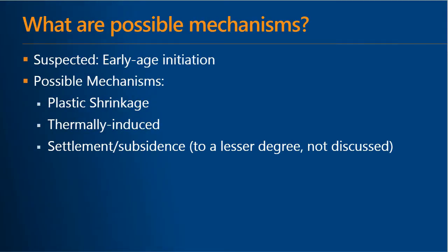So if we were to see this in the field, we would start thinking about early age initiation of those cracks. And so some of the crack mechanisms that immediately come to mind would be plastic shrinkage cracking, thermally induced cracking, and potentially settlement or subsidence, although that somewhat to a lesser degree, and I'm not going to discuss that here, but subsidence cracking tends to follow the reinforcing pattern of your element.